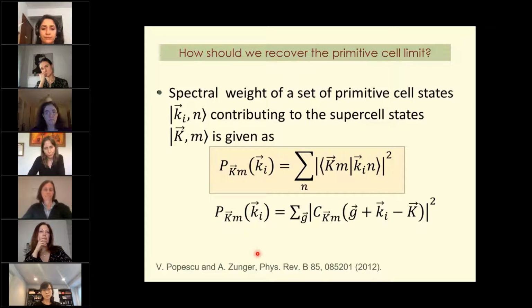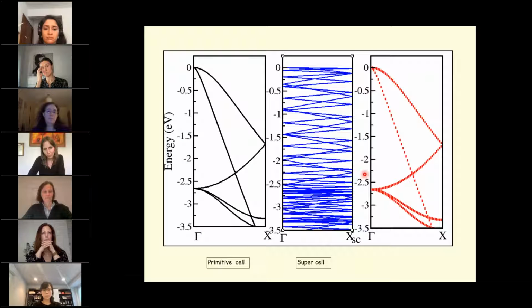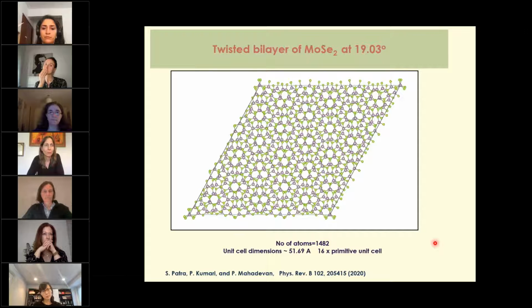What you do is you have the full-fledged wave function for the supercell, and you project those onto the initial unperturbed states, for instance. You do this analysis at each point, and you recover the initial primitive cell band structure, indeed, because there is no perturbation in this case. However, in the perturbed case, we also carry out the same analysis to see which states actually emerge from the primitive cell and what are the deviations that one finds.